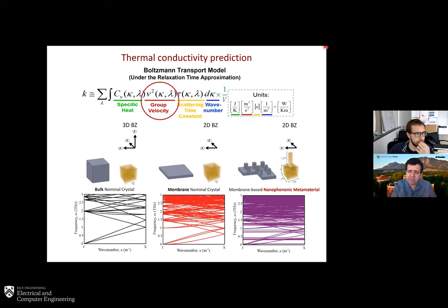You can see they manifest themselves as straight, horizontal, wavenumber-independent lines in the spectrum. And what they do is they couple. That's the heart of what we're talking about, this notion of coupling or avoided crossing that takes place between these resonances and the underlying phonon spectrum. In doing so, you get reductions in the slopes and reductions in the group velocities. And not only do you get it in a certain frequency range, you in fact get it across the whole spectrum, because you have millions of them. So that's really the main mechanism that we're utilizing.